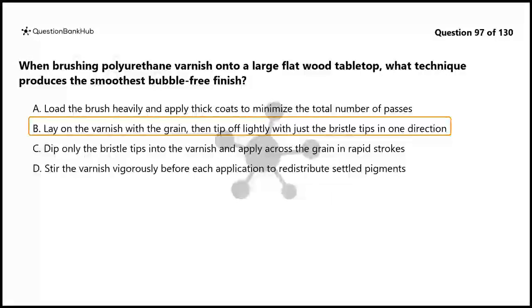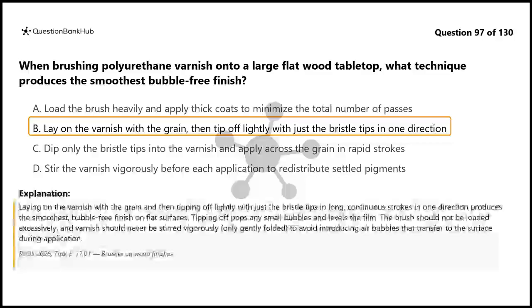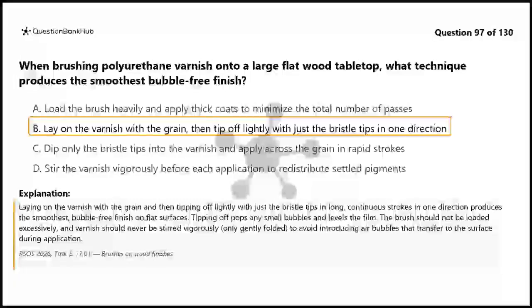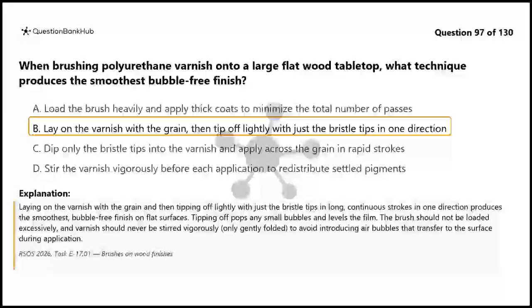The correct answer is B. Laying on the varnish with the grain and then tipping off lightly with just the bristle tips in long, continuous strokes in one direction produces the smoothest, bubble-free finish on flat surfaces. Tipping off pops any small bubbles and levels the film. The brush should not be loaded excessively, and varnish should never be stirred vigorously, only gently folded, to avoid introducing air bubbles that transfer to the surface during application.